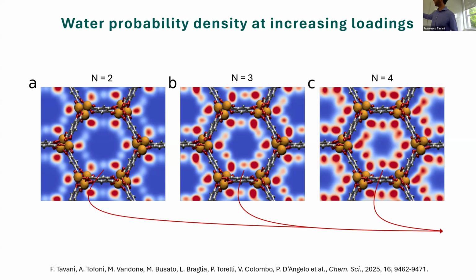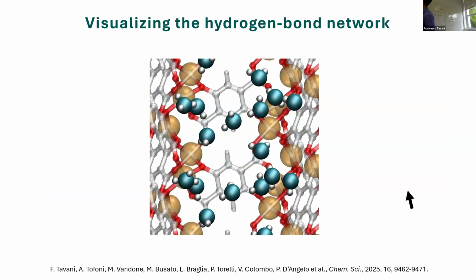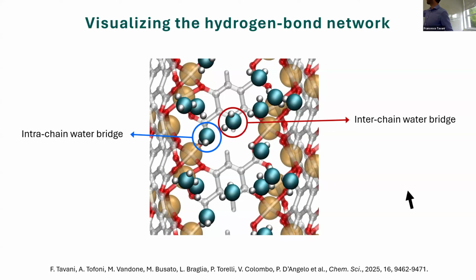So if we change this representation and look along the channel of the MOF-74 system, we can actually identify intra-chain water bridges. So you have different chains of magnesium sites, and these are like bridging chains. And water will first coordinate the open magnesium sites, and then there will be bridges created between one chain and another. And then you have interchain water bridges. So this is along the same chain, and this is along two chains that are close to each other.